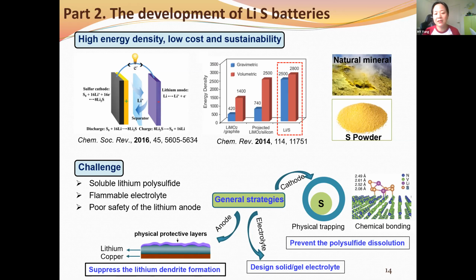The other main challenge for the lithium sulfur battery is that safety control for the pure lithium anode is still lacking currently. So the general strategies to rectify these three challenges are to suppress lithium dendrite formation, targeting the lithium anode material. For the electrolyte, we want to design a solid or jelly-like electrolyte. And for sulfur, we want to make a physical trapping, whether carbon or polymer, so that the sulfur is confined in this trapping system, which will prevent polysulfide dissolution into the electrolyte eventually.